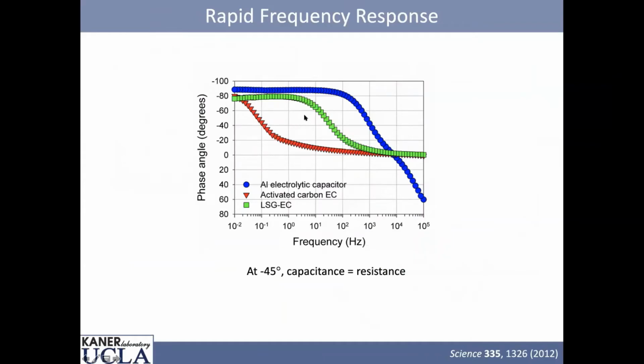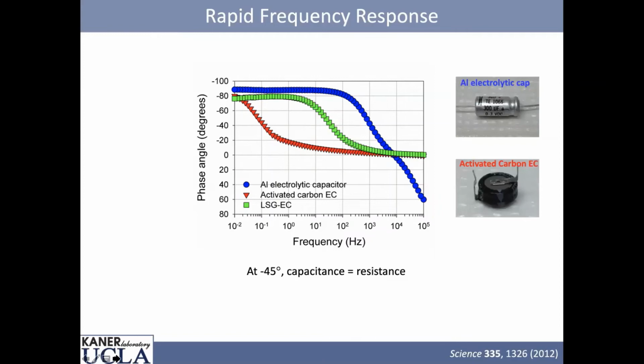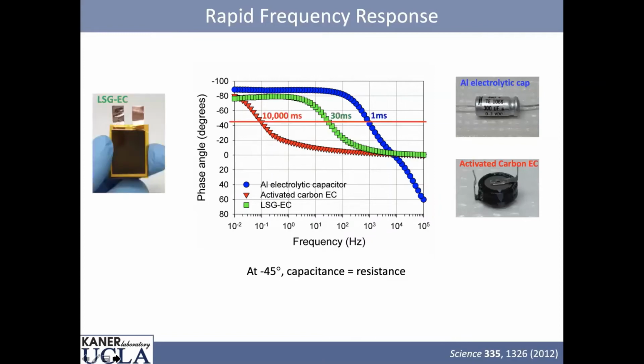This is one technical slide. We looked at the frequency response. And what's interesting is we can compare this to commercial materials and aluminum electrolytic capacitors. So first of all, a commercial material, which is made from roasted coconut shells, has a time constant of about 10,000 milliseconds. Our material is over 300 times faster. We're at 30 milliseconds. And an aluminum electrolytic capacitor runs about 1 millisecond.